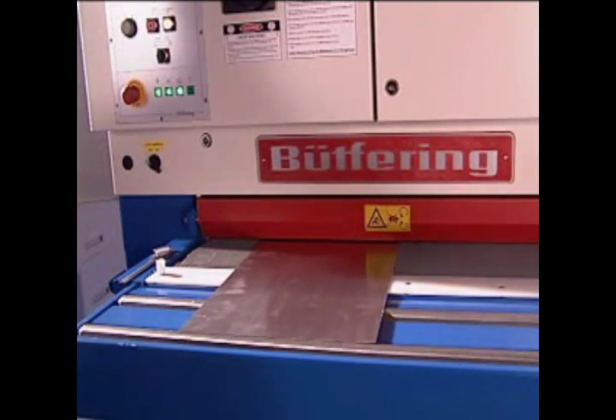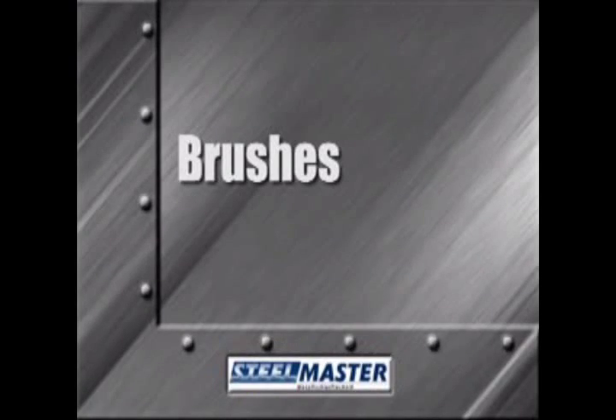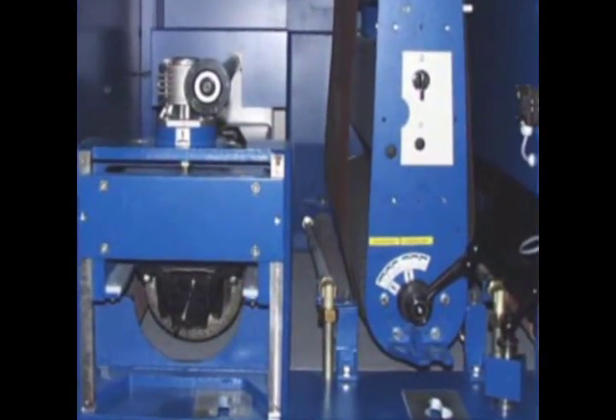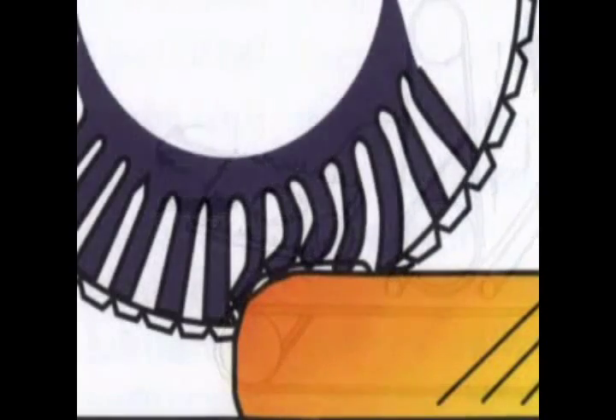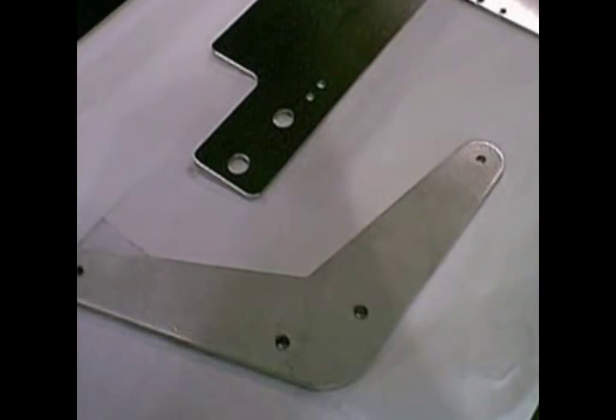This also has a major effect on your abrasive belt life, as one speed does not suit all applications. The other variable is brushes. In the past few years, manufacturers and job shops alike have realized the benefits of belt-brush combination machines. In these illustrations, we show the effect the brush has on the deburring process. As you can see, the abrasive belt with a soft contact drum has a high abrading pressure on the burr, but low impact on the surface of the material. The soft contact drum, combined with low speed on the abrasive belt as well as the conveyor, allows the belt to work only on the burrs. The brush follows behind the belt and reaches into the holes and over the edges, removing the secondary burr. This process works so well that you can deburr galvanized steel without removing the coating.